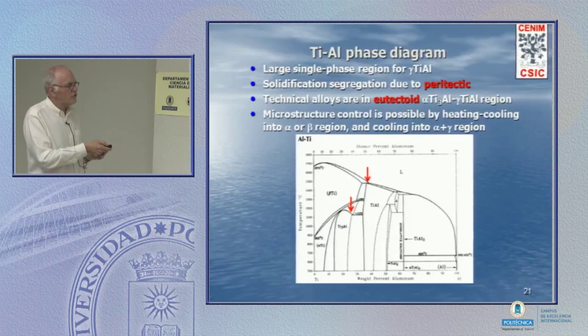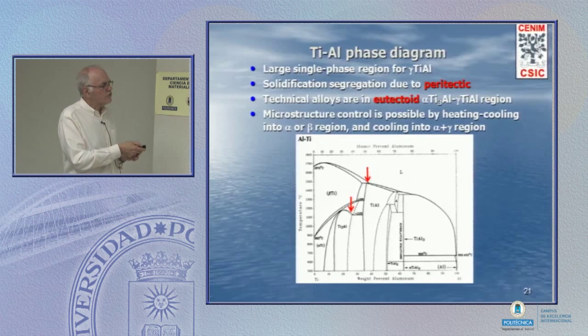Also of interest is Ti3Al, which has a different crystal structure, and most of the research over the last 20 years has looked at alloys in what's called the alpha-gamma, Ti3Al, TiAl composition range. So not with 25% aluminium, not with 50% aluminium, but somewhere in between where you've got a mixture of the two. Now, of great interest here for these alloys, between 25 and 50% aluminium, you have a eutectoid.